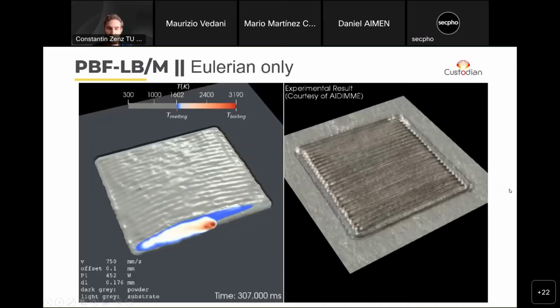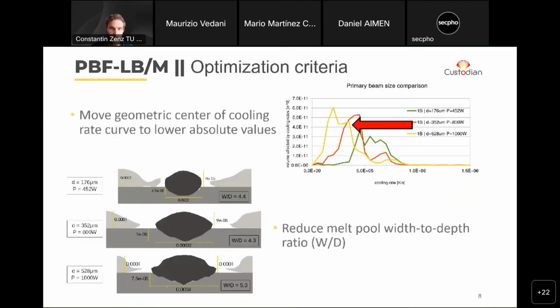So if we continue on, we heard in the previous presentation already that we need to somehow lower the cooling rates in this process within a certain temperature range. So we call this critical temperature range the brittle temperature range, and this is a very high temperature. It's in the region between solidus and liquidus temperature and slightly below the solidus temperature of the material, and it depends obviously on the material. And so within this temperature range, we want to lower the cooling rate. So what we did is in each simulation that we performed, you have a graph on the top right. We measured the cooling rate.